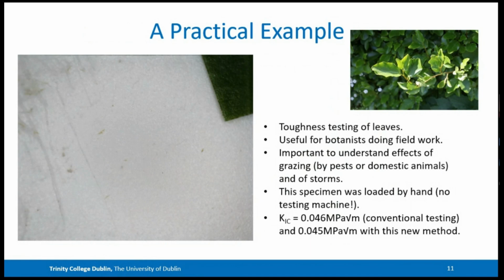So with that very simple setup, you can quite easily measure the crack openings. And plugging that into the equation, we got a fracture toughness value exactly the same as with conventional testing. So we've proved in principle that it can be done, at least for leaves anyway.